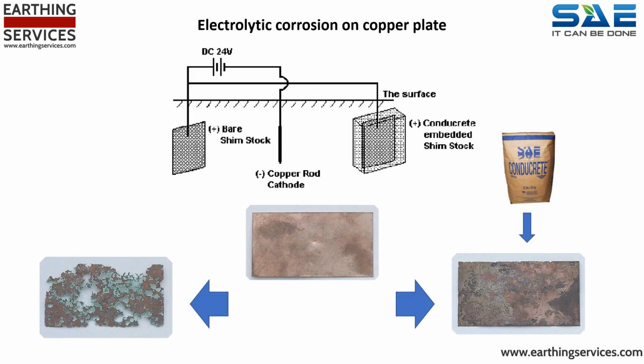Some companies do not use earth rods and instead use copper plates, lattice mats, or even bare cable. As copper is a non-ferrous metal, there is often a misunderstanding that it will not deteriorate. However, whenever there is an electrical discharge, there is electrolytic loss of the conductor. Here we see ageing evidence from testing which demonstrates a bare copper plate and one encased in Conducrete after repeated electrical discharges. As you can see, the bare plate has badly deteriorated.